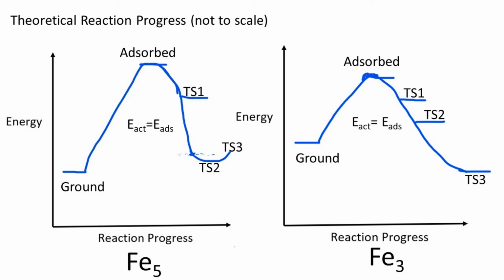These results indicate that there may be surface carbon interactions in some areas of the chain, while in others there would be polymerizations. This combination of surface bonding and polymerization may provide a more complete reasoning for seasoning's tough, hydrophobic nature. Of course, some of the assumptions made in this study are quite generous, such as a perfectly clean adsorption site. Future work could include site competition, or it could try to simulate the effects of oxygen desorbing from the iron sites into the oil, which could also start the polymerization reaction.